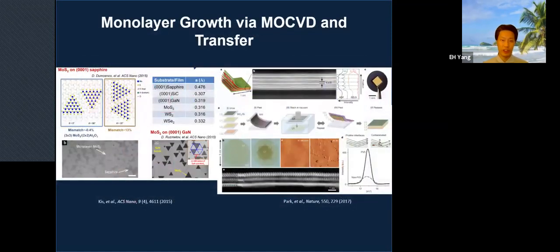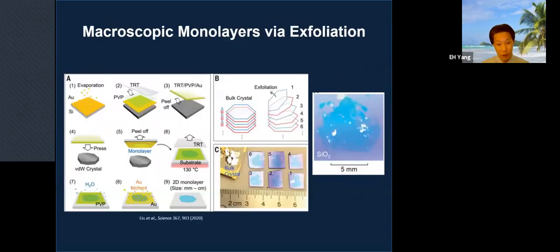Better growth was achieved using metal organic chemical vapor deposition, or MOCVD, to grow a monolayer over the entire wafer. Although the problem was the small grain size, which is also another problem for electronic applications in this case. All right. Most recently, a 2020 paper published in Science showed macroscopic monolayer exfoliation up to 5 millimeters in size. So this is a kind of state of the art, right? With the best fabrication results that you can find in this material so far.